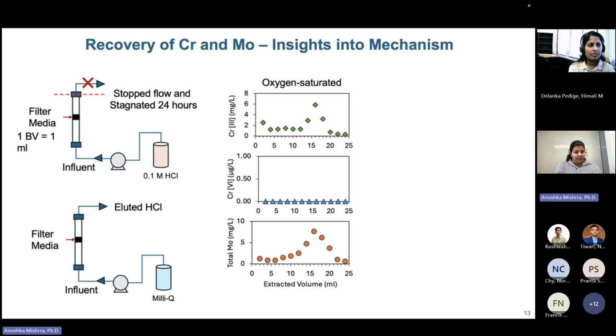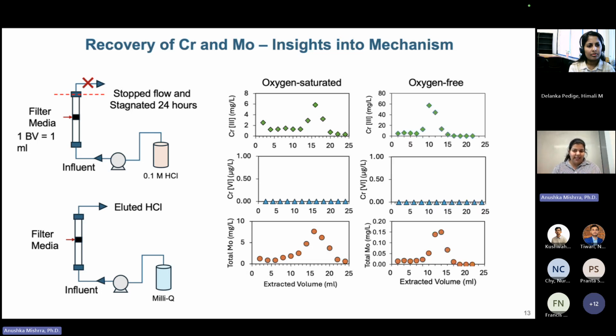This proved very helpful because it did not really dissolve the MoS2—it's very stable under acidic conditions. We also noticed that through this process, all the chromium that came out of the material during cleaning was chromium(III). So we're looking at non-toxic hazardous waste coming out of the cleaning process, which lowers the cost of water treatment.